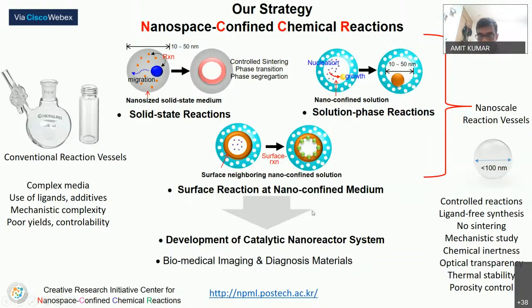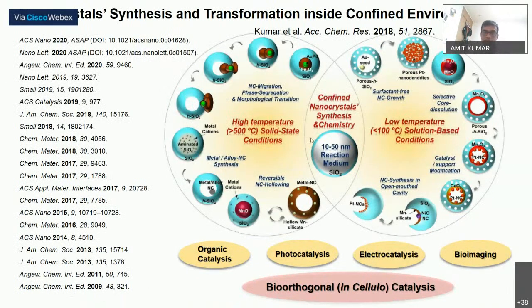Two years back, I summarized all these strategies developed during the last few years and published it in Accounts of Chemical Research. As you can see, using this chemistry we can generate various morphologies where nanoparticles are selectively functionalized on either the interior or the exterior, and we can generate various structures of hollow nanospace within the silica-confined environment. These resulting nanostructures can be applied for organic catalysis, photocatalysis, and, if you remove the silica, electrocatalysis, and they are highly useful in many bioimaging applications. Recently we found them very useful in bioorthogonal catalysis.